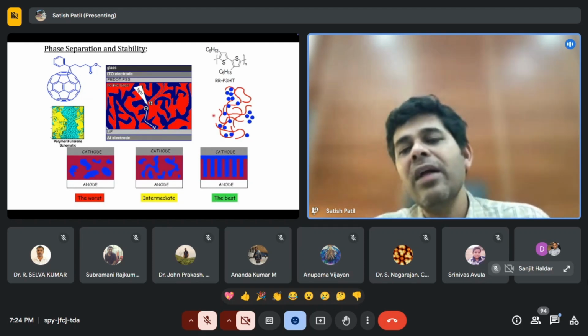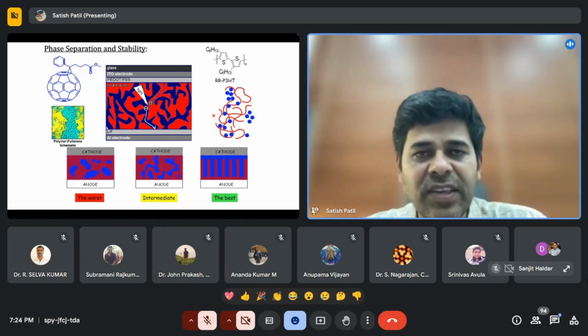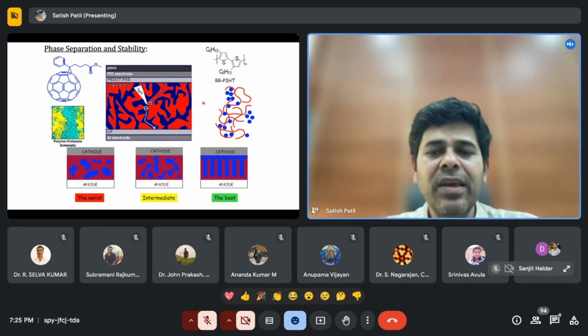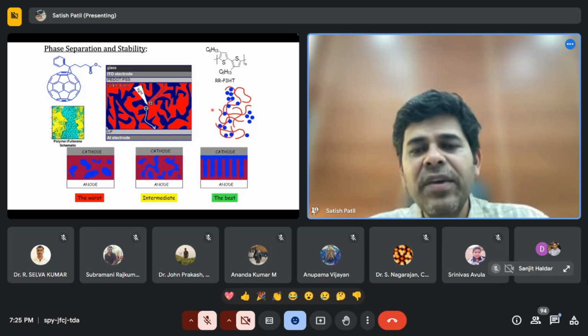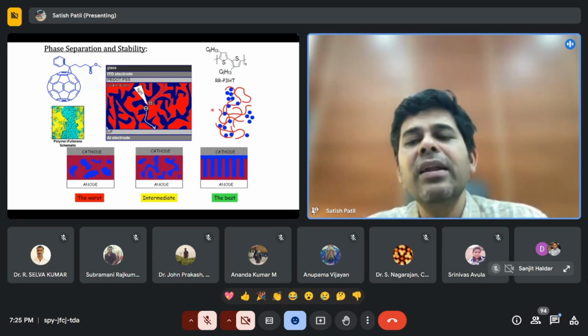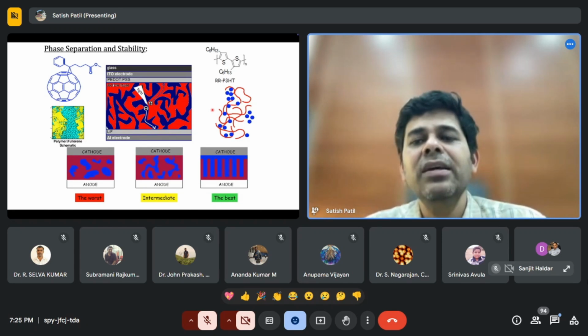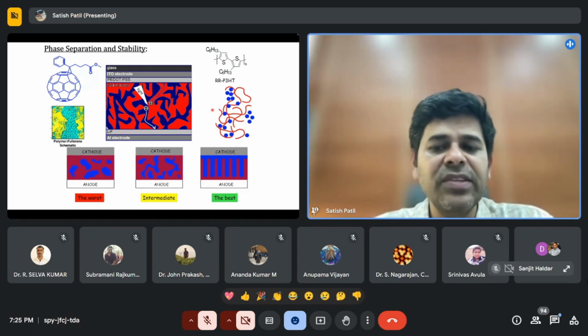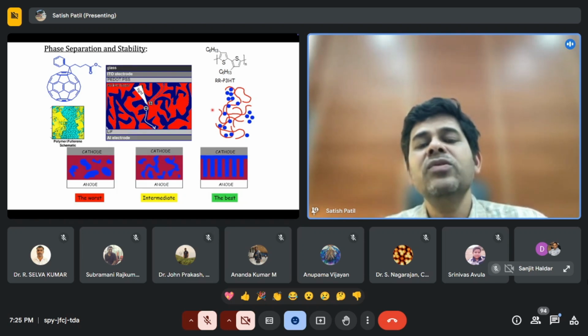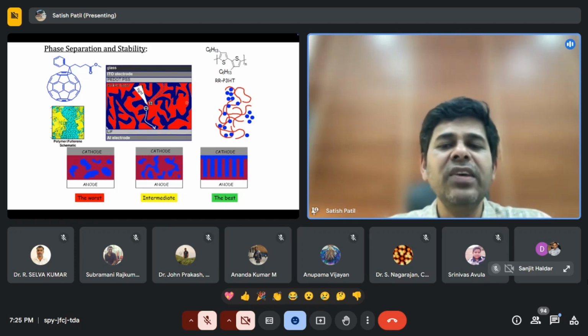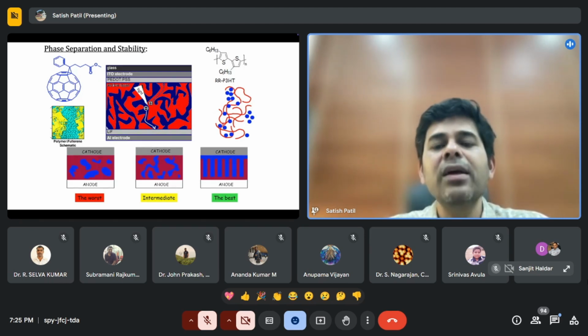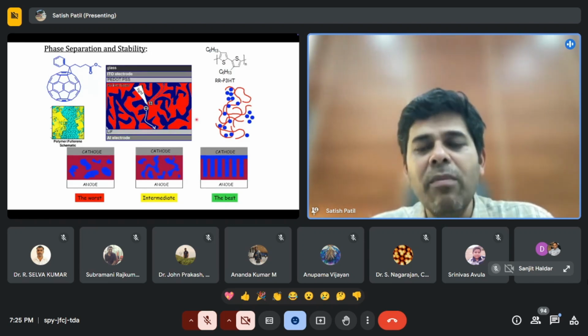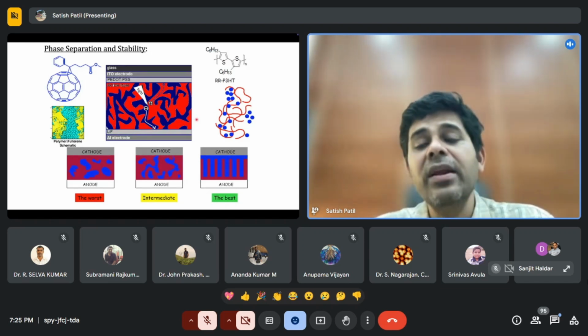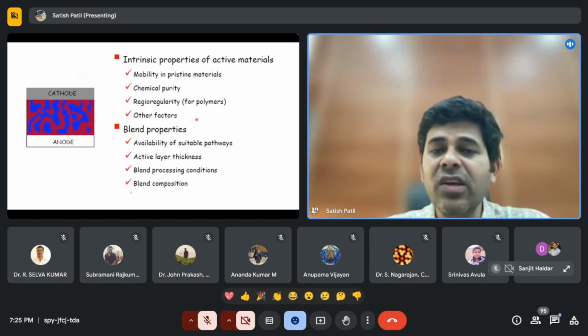But however, there are other limitations in organic solar cells. For example, phase separation and stability, because these materials eventually phase separate. Phase separation is a big challenge in the field that really hampers the stability and lifetime of these solar cells, because as a function of time, this is a physical mixture of a donor and acceptor. You use a conjugated polymer and N-type fullerene, you mix them together. But then phase separation is a major problem in this field at the moment. So people are working out how to freeze this phase separation and make very efficient solar cells.